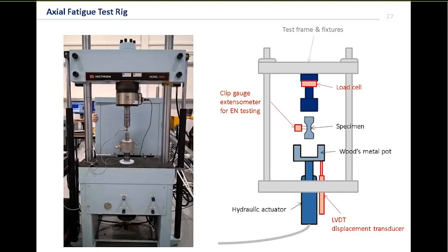Now, one of the main things with a test rig is to keep your component aligned. You want perfect alignment. In this example, you can see a Woods metal pot being used. Woods metal is a bit like solder. It's a low melting point metal. We heat it up, in this case under boiling water, and then we can lower the specimen and the end grips into that. Then we can cool it off, and it sets to form a hard metal, but we get perfect alignment. It takes a little bit longer with Woods metal to set up each test, but the benefit is the alignment is better. So we tend to use those wherever we can.